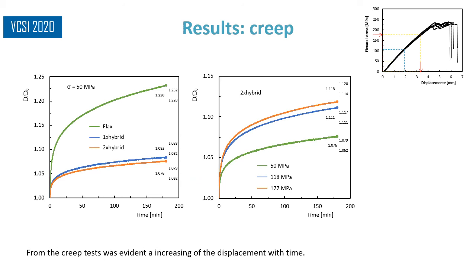Regarding the creep tests, the tests were carried out in the same machine and with similar samples at room temperature during 180 minutes, where to compare the different laminates a fixed stress of 50 megapascal was applied and the displacement recorded during the loading time. The figure shows the results in terms of average curves, besides the average values obtained after 180 minutes, closed round symbol. The figures also show the respective maximum and minimum values for each stress.